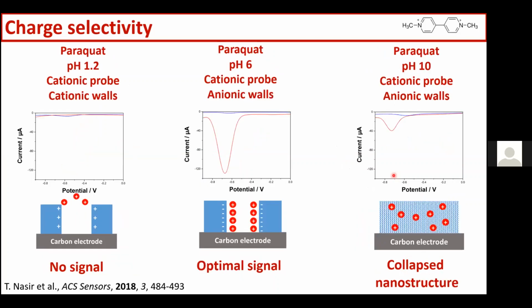We also looked at the effect of the pH on the signal of paraquat, and if we go to a pH around 1, you can see that the film is going to be positively charged, and here we completely suppress the response for the paraquat due to electrostatic repulsion. The isoelectric point of silica is between 2 and 3, so it will indeed be positively charged. pH 6 is what I showed you previously, where the probe is cationic and the walls are negatively charged.